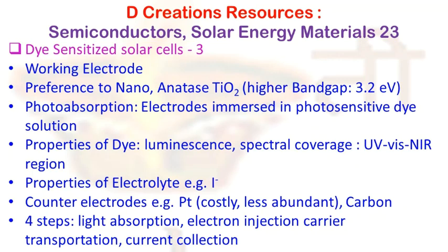Now it is preferred if the periphery of the dye is hydrophobic to enhance the long-term stability of cells, because it results in minimized direct contact between electrolyte and anode, and otherwise water-induced desorption of the dye from the TiO2 surface can appear, and if that appears, of course the stability of the cells is going to reduce.